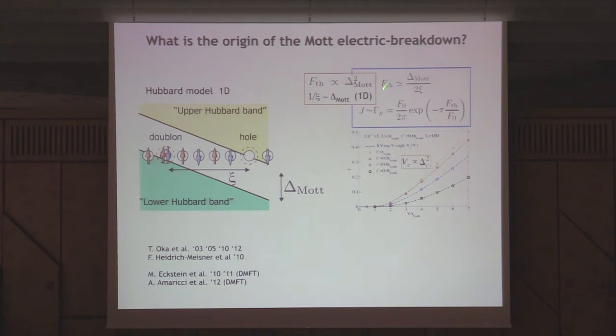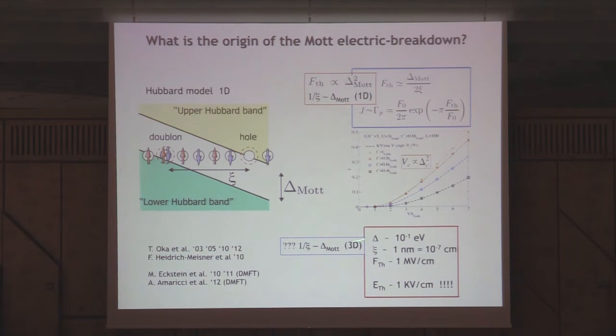And there, the threshold field, which is expected to go as the Mott gap divided by eta, goes as delta square over eta, like delta Mott. So if you put numbers to that, you expect delta to be of the order of a fraction of an electron volt, and eta conservatively a nanometer, which is already pretty large. So you see that the threshold fields that you may expect are megavolt per centimeter. However, in the experiments, this is kilovolt per centimeter.